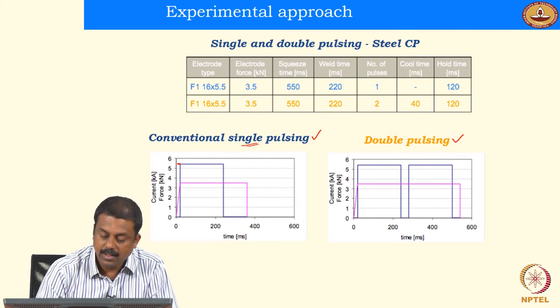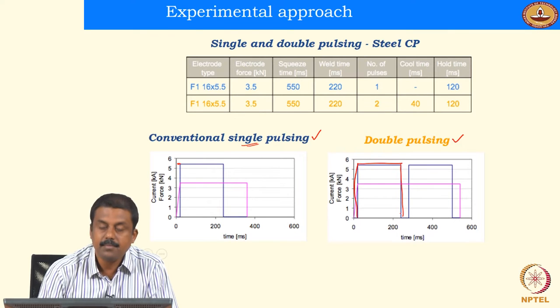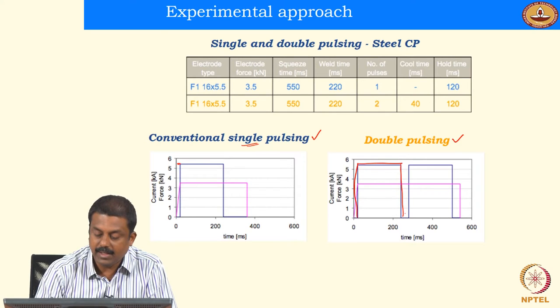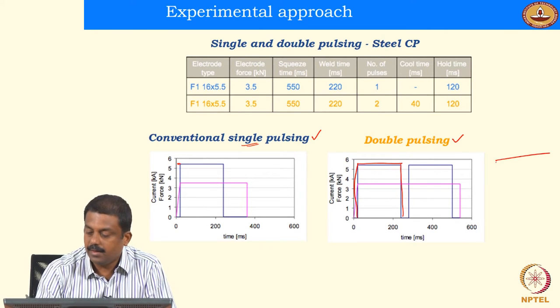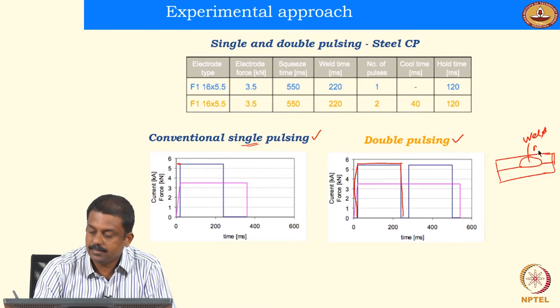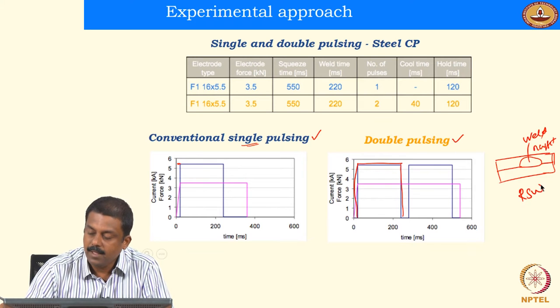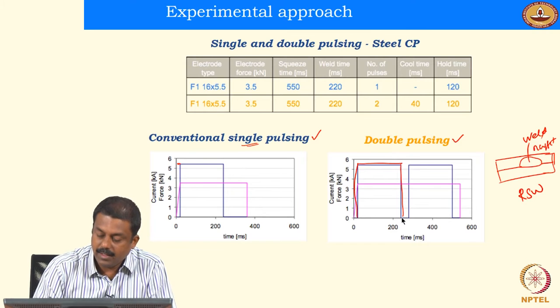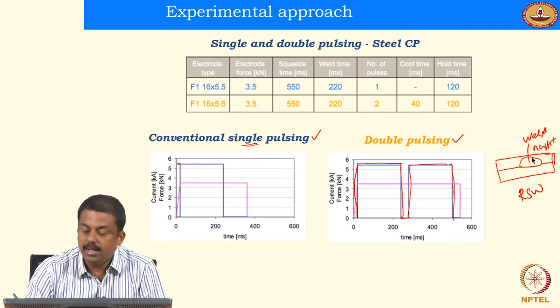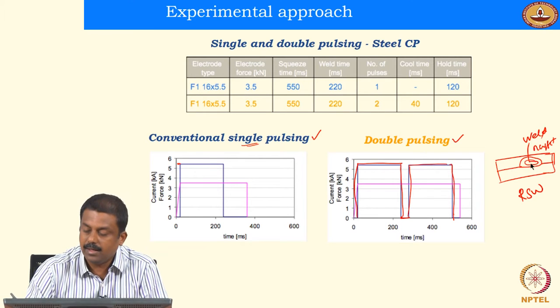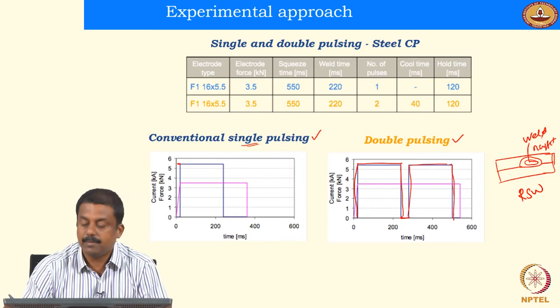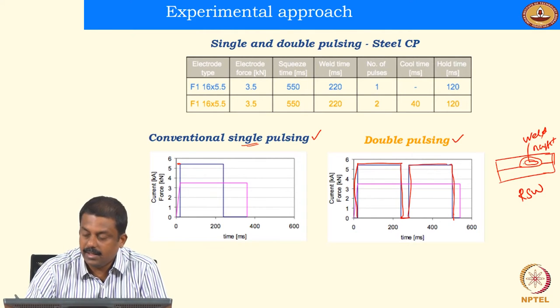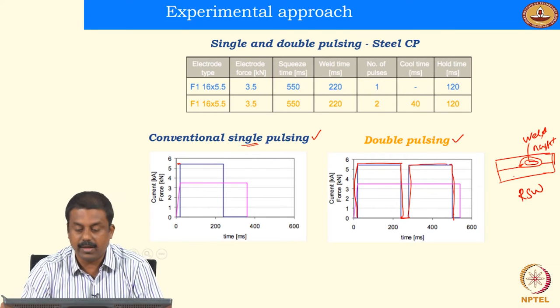In a single pulsing, we have a single current pulse, and by giving this pulse and the load, we achieve a weld nugget of, say, so and so diameter. We get this weld nugget diameter in resistance spot welding. So now, instead of giving a single pulse, after the first pulse we will also apply a second current pulse, as shown in this figure. And by doing so, we may also remelt the first nugget which is formed during the first pulsing, and that can favorably influence the alloying elements which are segregating at the weld center line. Okay, we will see in the subsequent slides how we can do that.